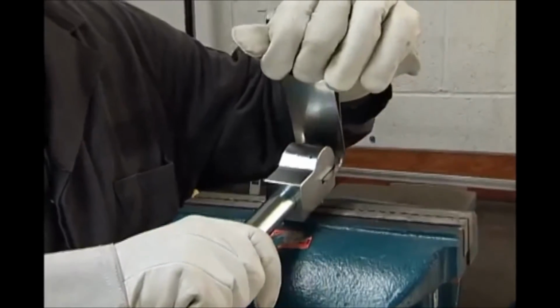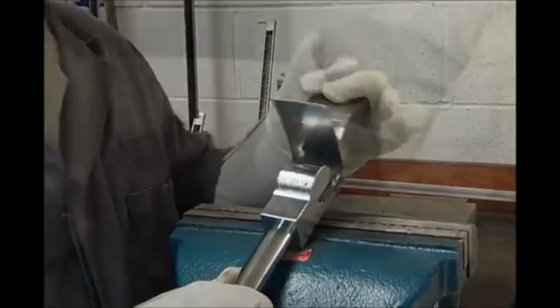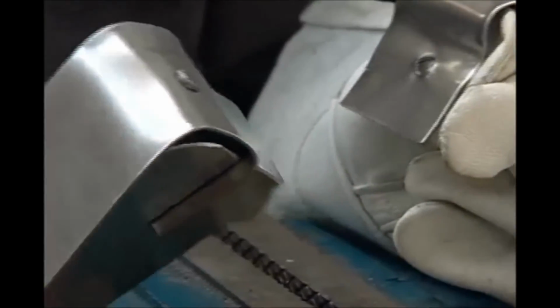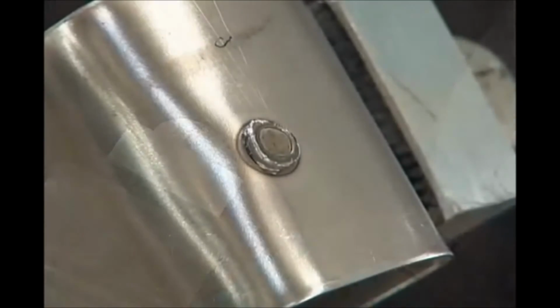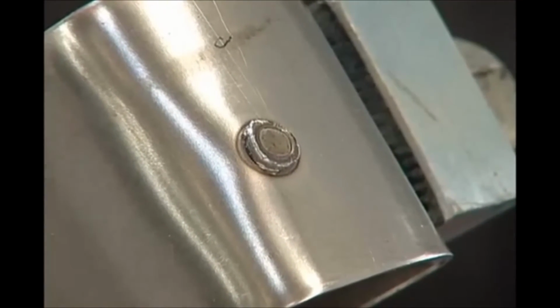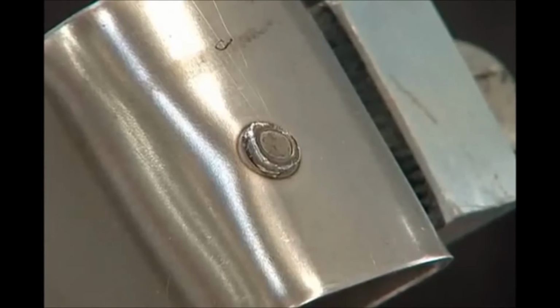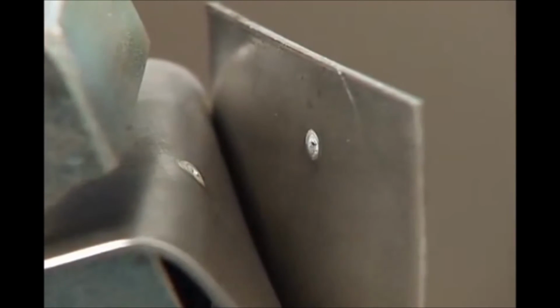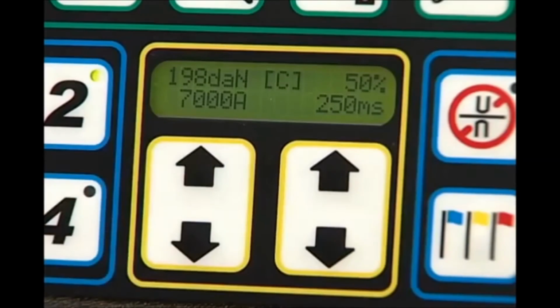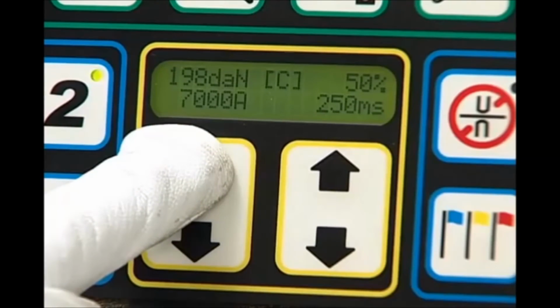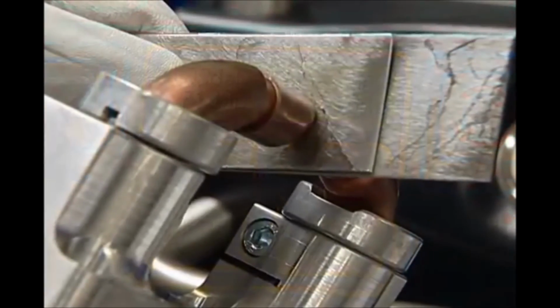The weld nugget should peel away and leave a hole in the opposite coupon. The recommended weld nugget diameter for this sheet metal thickness is 5 millimeters. If the pieces break apart cleanly, the weld current is too low. If the current setting is too high, there may be a splash of molten metal present between the 2 coupons. In either case, adjust the current setting and test again.